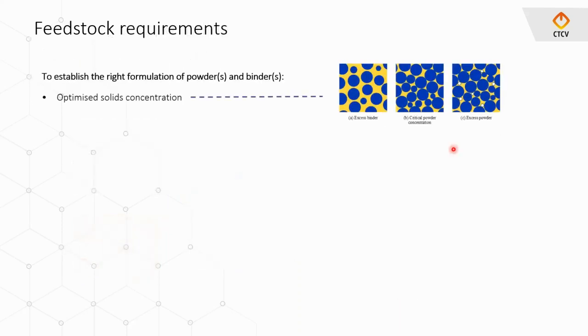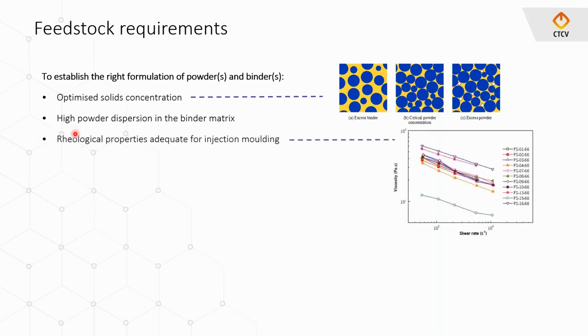Okay, so the feedstock is a very critical component in this technology, and I will point out some aspects of the feedstock. We have to optimize the solid concentration. We don't want to have excess binder nor excess powder. We have to find the precise optimized concentration. Of course, we have to have homogeneous dispersion of the powder through the binder matrix, so it is very critical in the mixing step.